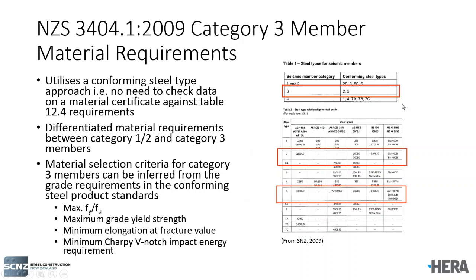So we can see here this Table 1. As long as you chose a Type 2 or a Type 5 steel, which essentially was an L0 steel grade, either in 250 or 300 MPa yield, or a grade 350 L0 steel or equivalent, that was all you needed to do. You were not required to check any data from a material test certificate against Table 12.4.